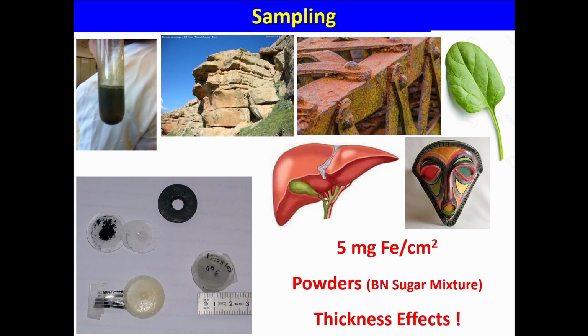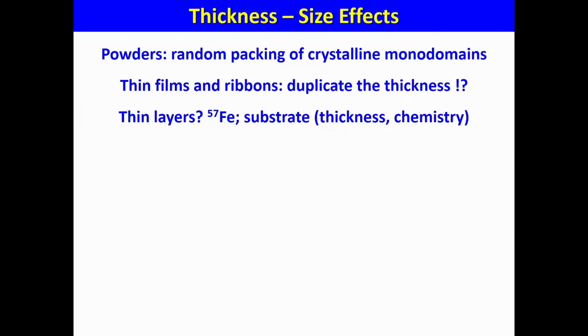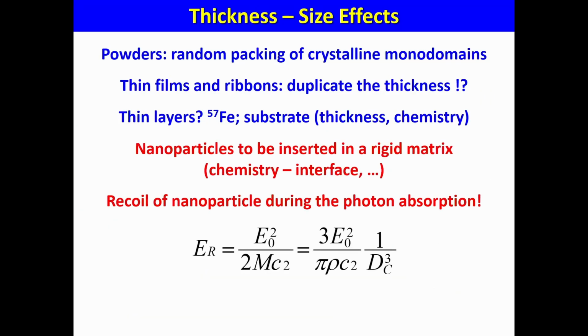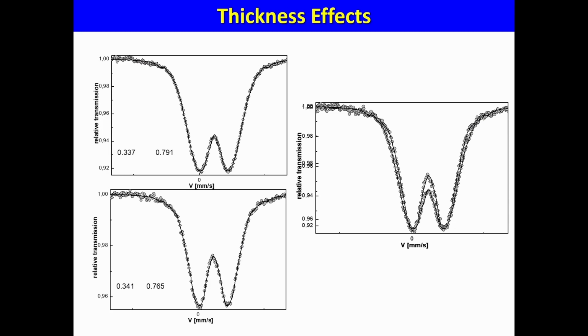Okay, so you have to remember the quantity is quite small, 5 milligrams of iron per square centimeter, providing it's easy to establish the quantity. If you put much more, you will change the profile of the spectra. So look, here are two spectra on the same sample, on the left side, but not the same quantity. Of course, after you can imagine a lot of very sophisticated models, but finally, one is due to a thickness effect. Of course, it's possible to make some corrections, but it's better, if you have the possibility, to start with the ideal quantity to prevent sophisticated complications.